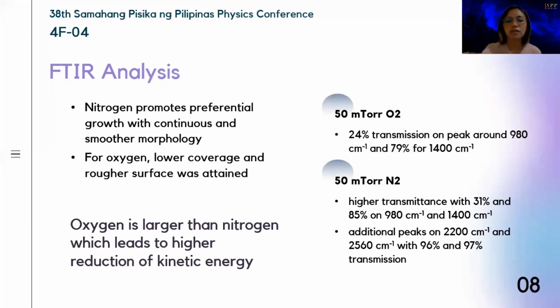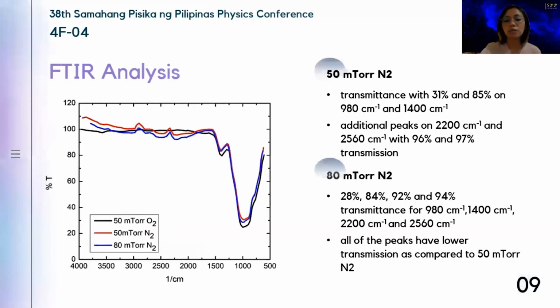The pressure of nitrogen was also increased to 80 millitorr, and the FTIR analysis for this is shown in the blue line. These peaks were similar to those of the films deposited under 50 mTorr nitrogen. The 980 and 1,400 peaks show a 28% and 84% transmittance, and for the other two peaks, the transmittance was 92% and 94%. All of the peaks for 80 mTorr manifested a lower transmission as compared to the films under 50 mTorr.